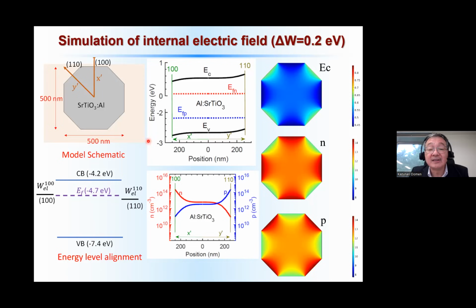Then we carried out the simulation. And as you see here, along the X prime axis, the internal electric field points downward like this. This kind of internal electric field accumulates photoexcited electrons on the surface. On the other hand, along the Y prime axis, the internal electric field is actually upward. In this case, the photoexcited holes are likely to accumulate on the surface. But this is actually a two-dimensional system, so the actual situation is like this.